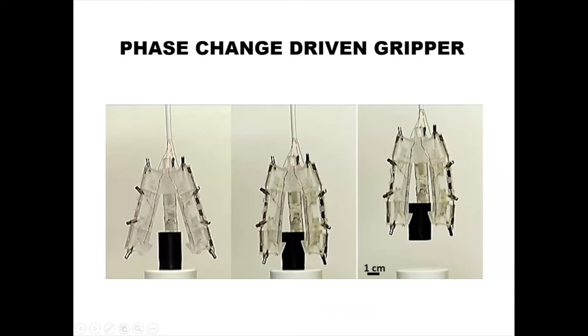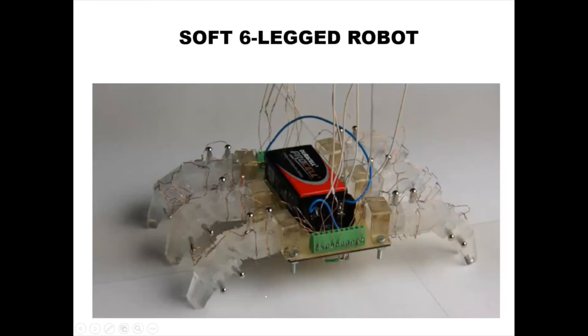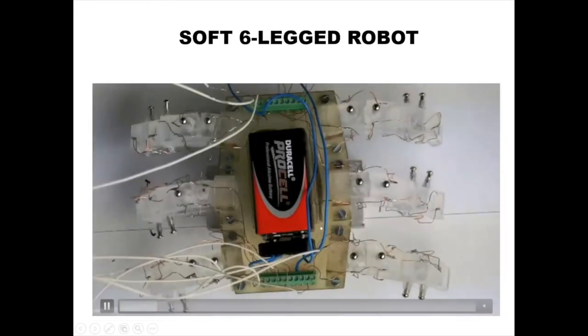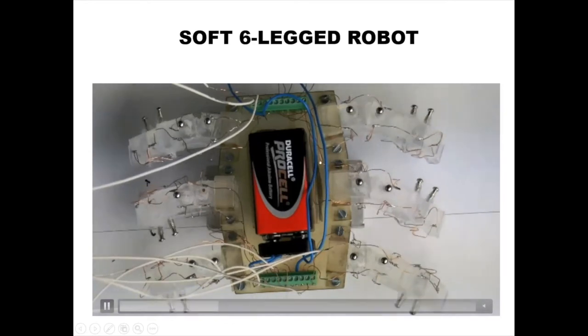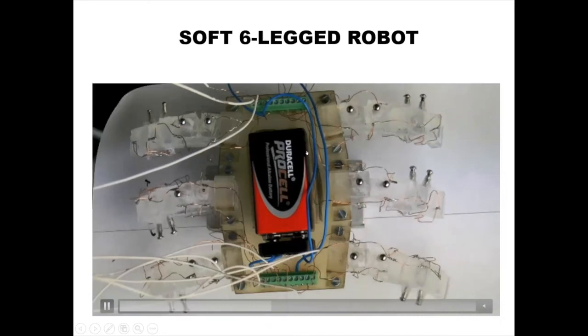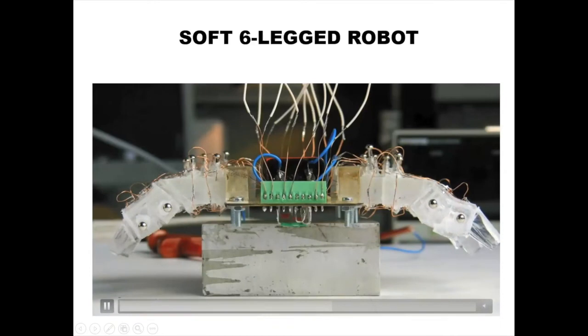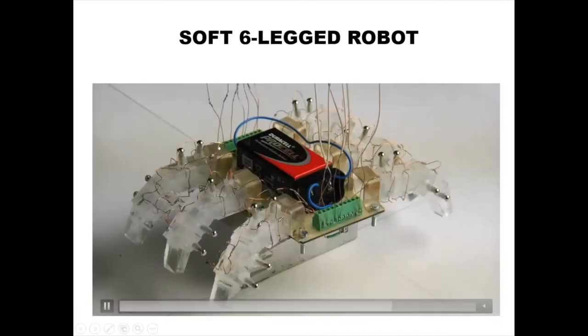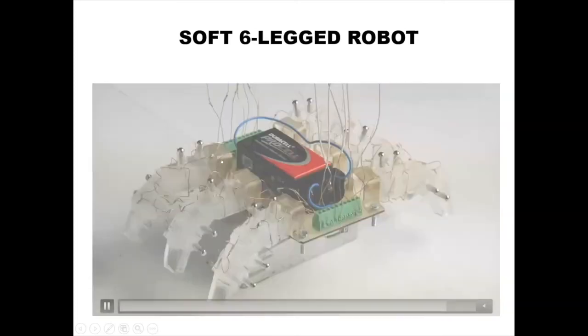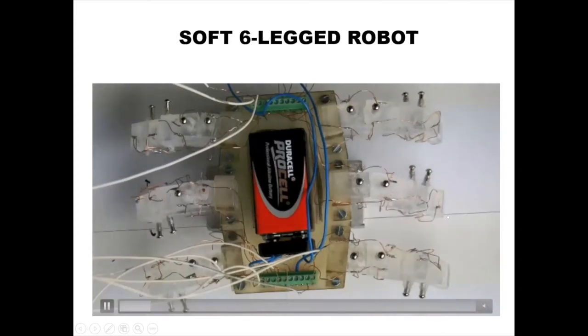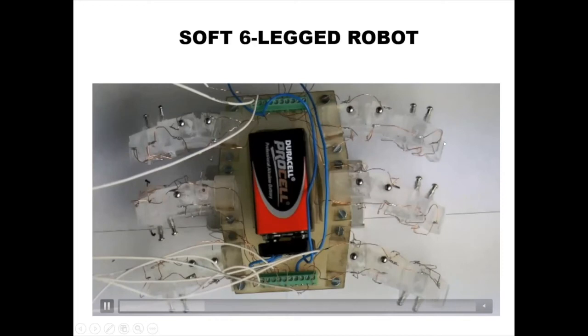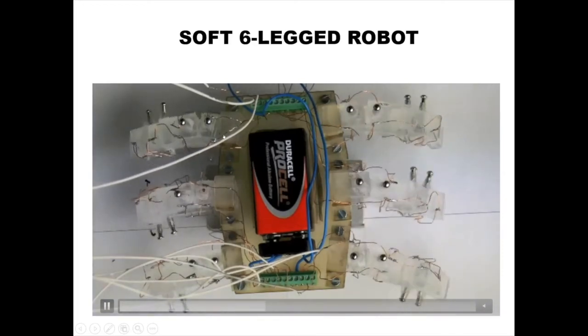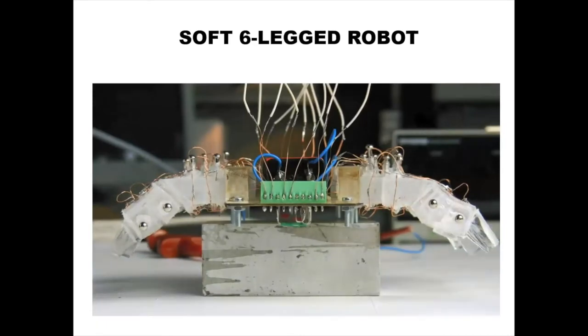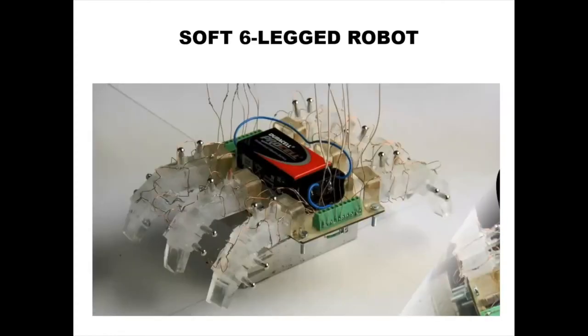We also incorporated stretchable electrodes on top to monitor the bending action through the change of resistance. It's not very pretty, but it was a first attempt. And I think it shows a little bit what the challenges are. So we made this little robot that's powered with a conventional battery that can lift and move its legs. I should say it was quite incapable of really walking because the body was too heavy. But you can see we have different motions, forward and also downwards. I think it's a pure matter of design. Also, these elastomeric materials are quite heavy, and this is a challenge.